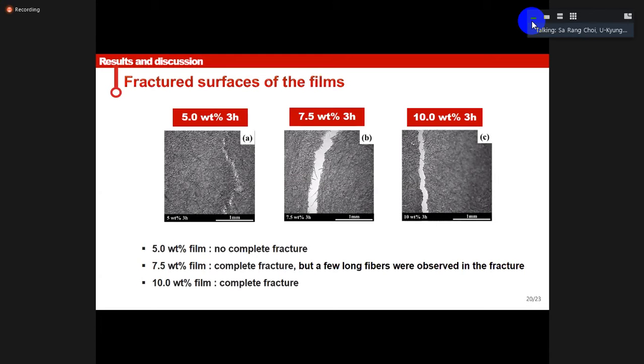This picture supports the data shown in the previous graph, which is the fracture surface of the film after tensile test. When the tensile force was applied to the 5% kneaded film, a perfect fracture was not made. In the case of 7.5%, it was completely fractured, but a few long fibers were observed between the fracture. Whereas the 10%, the most micronized, showed clear fracture. So it has the lowest tear index and it has the highest tensile index.